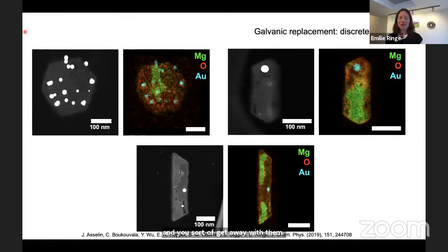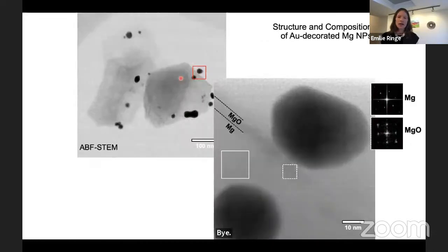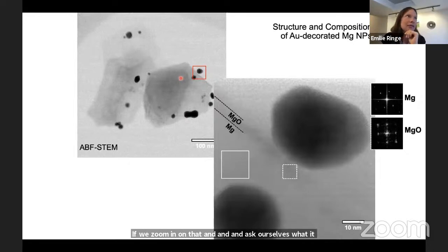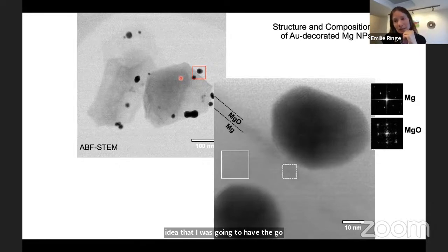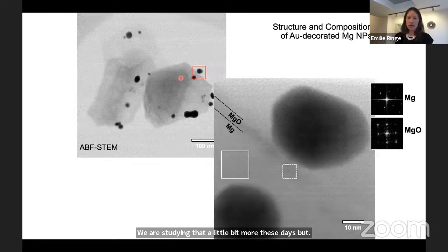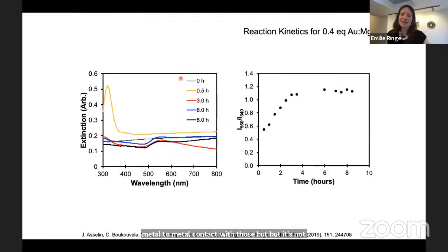We can map, of course, the elemental distribution around these, and we can see that there is gold, and the amount of magnesium actually decreases on these structures. It's obviously etched by this galvanic replacement by the gold. If we zoom in on that and ask ourselves whether there's an oxide layer, it turns out there is. So this idea that I was going to have the gold in intimate metallic contact with the magnesium actually just didn't work. It seems that the magnesium oxide reforms at that interface. We are studying that a little bit more these days, but so far we still don't get a magnesium-to-metal contact with those, but it's not going to stop us. It never stopped us with aluminum, for instance.